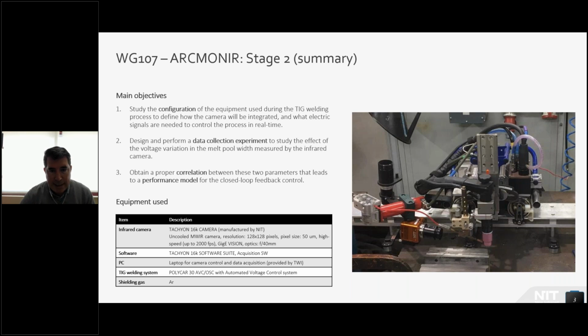In the image, you can see the equipment that we use for this experimental phase in stage 2. We have the infrared camera, the orange box that you can see on the left of the torch. It's an uncooled camera operating at 1 kilohertz with detection between 1 and 5 microns. All the images are transferred to the PC, which we will analyze later using our software. This camera is manufactured by us. And then we have the TIG welding system, which is made by Polysoude, and it has an automatic voltage control system into which we intend to integrate our closed loop control.